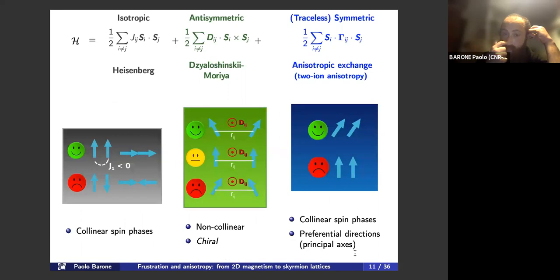We can also have a look at the competition between these terms. We know that the Heisenberg interaction would favor a collinear spin phase, so spins align parallel or anti-parallel depending on the sign of the interaction, but it does not provide any information on the global direction of this collinear phase. The Dzyaloshinskii-Moriya interaction instead would favor a perpendicular configuration of the spins, but not only that, it also has two other important effects. One is that it selects the rotational plane where the two spins rotate one with respect to the other, and also the handedness of the angle between the two spins. This is simply related to the axial character of the vector product between the spins.